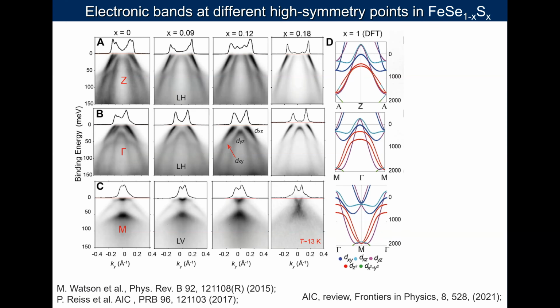If we look at the gamma point, similarly, we can see the dxy band and how it changes with the substitution, and we only have a crossing here. But the most striking effect is the electron pockets here. We are supposed to have two parabolic dispersions, and what happens is that only a weak parabolic dispersion is often seen. The second one is weaker in intensity, but then below the Fermi level there is a very unusual splitting and change in the intensity of the spectral weight, as if we develop some sort of gap below the Fermi level.